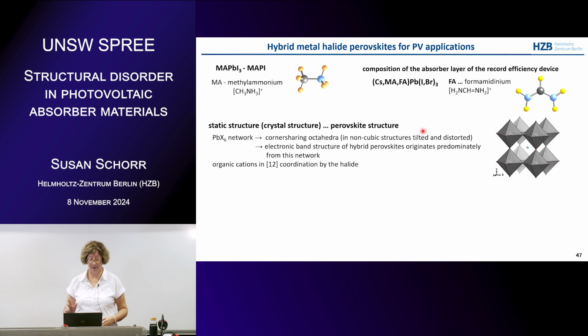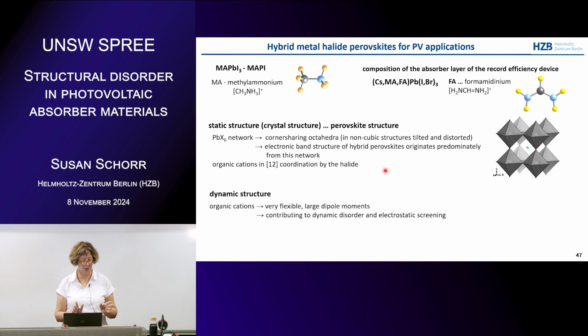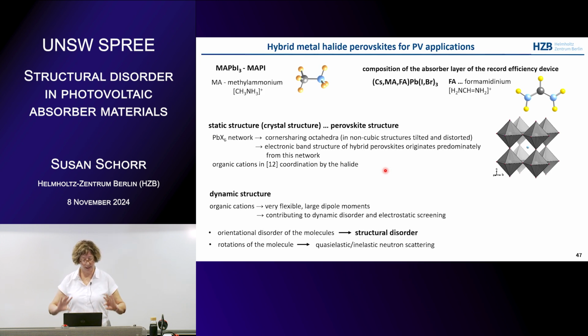They all crystallize in the perovskite structure. So the perovskite structure is defined as a network of corner-sharing octahedra, as shown here. And if the structure is not cubic, they are tilted and distorted, like in these chalcogenides. But you have not only this static structure, which we looked at before for all the other materials. Due to the organic cations, they also have what is called a dynamic structure. So these organic cations are large dipole moments in the material which are very flexible. So they can have different orientations, which is what we call structural disorder, or they also can rotate. So they can make flips. And we studied this as well by quasi-elastic and inelastic neutron scattering.